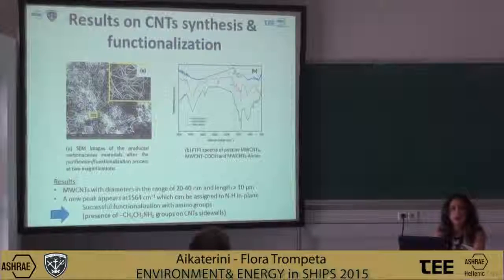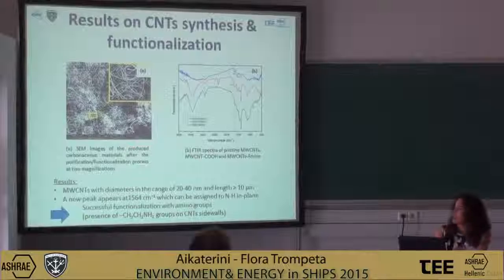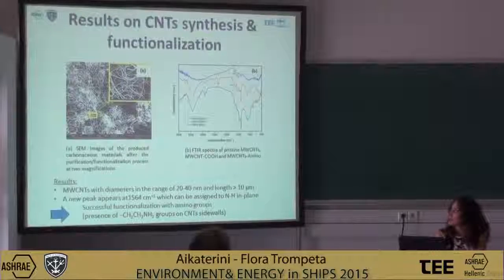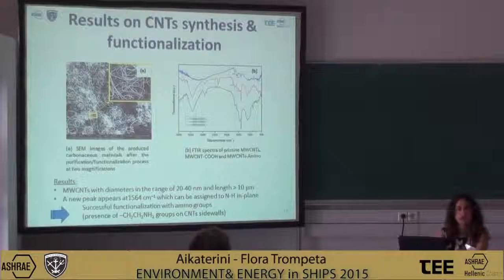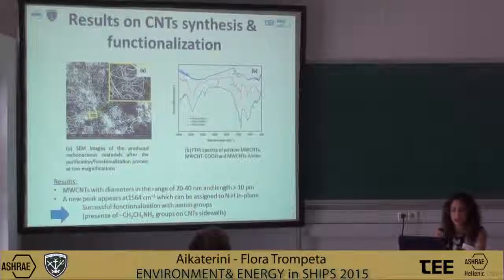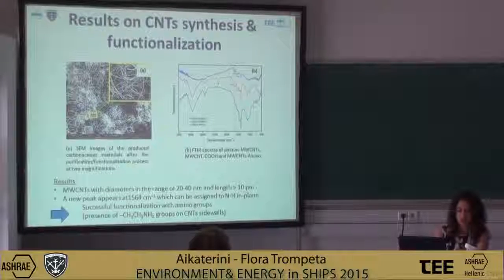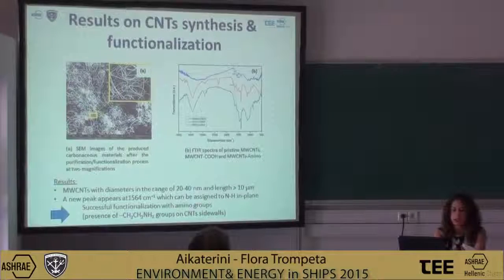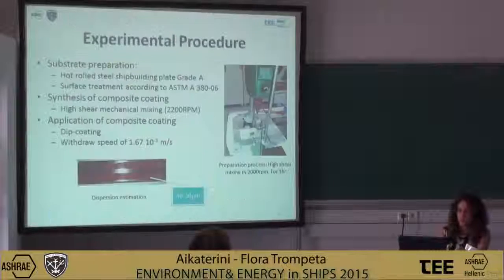peak that appears at 1564 wavenumbers, which can be assigned to the nitrogen-hydrogen in-plane bending. Also, we can observe from the SEM image that the functionalized CNTs have this kind of morphology, and they have diameters in a range from 20 to 40 nanometers and a length over 10 micrometers. The FTIR spectra show that the functionalization was successful and the amino groups were grafted on the CNT sidewalls.